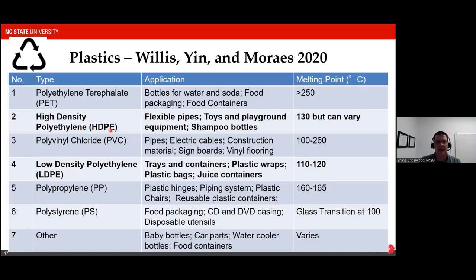High density polyethylene is the kind of material that we use in pipes that you might come across in playground equipment and things like that. You might also find high density polyethylene in very, very stiff plastic bags, or even some soft bottles that we might encounter. The other kind of plastic that's relevant is low density polyethylene. Low density polyethylene is the very thin plastic bags that we might use for wraps around food. We might use low density polyethylene bags for shopping purposes or other kinds of things. And what you'll notice about high density polyethylene and low density polyethylene is that these tend to melt at about 130 degrees Celsius, or in the case of low density polyethylene, somewhere between 110 and 120 degrees Celsius.